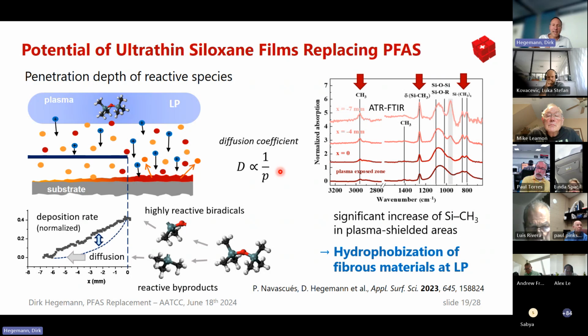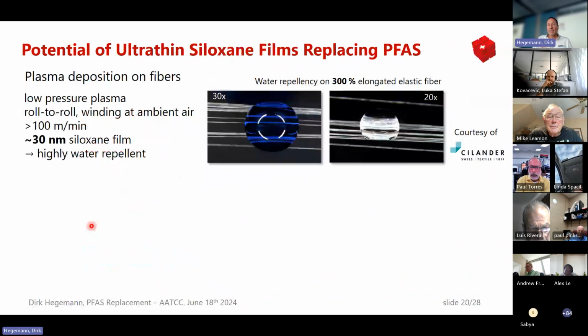And on top, if you select the chemistry right, it can be this molecule, meanwhile we are also using other molecules, you can create a situation where you form different kinds of reactive species with different reactivities. You have, for example, one highly reactive radical that deposits more on the top, or just at the, let's say, inlet into a structure. And then you can also create less reactive species and they diffuse much further into the textile structure. This way you can optimize the penetration into a textile structure and thus also the hydrophobization of fibrous materials. That has indeed been optimized over recent years.